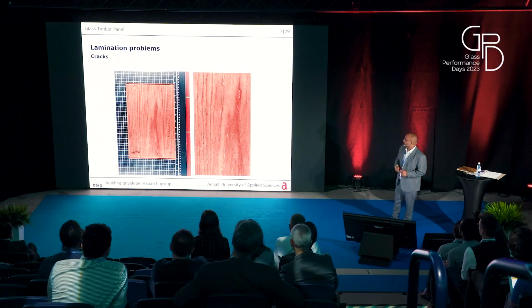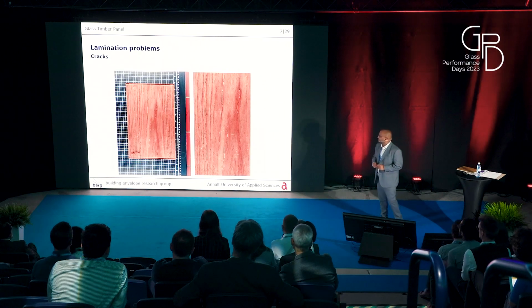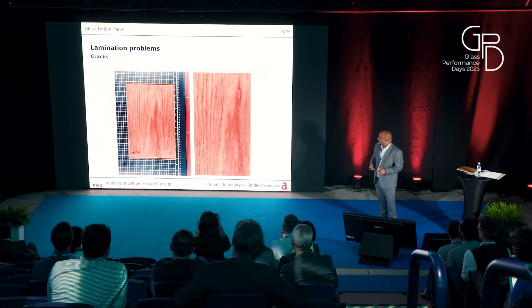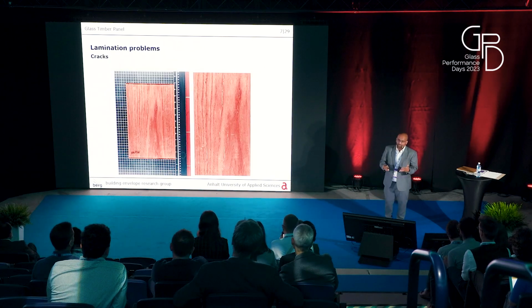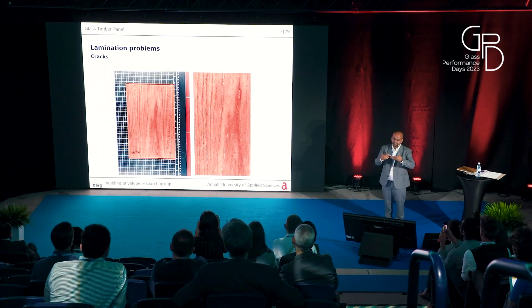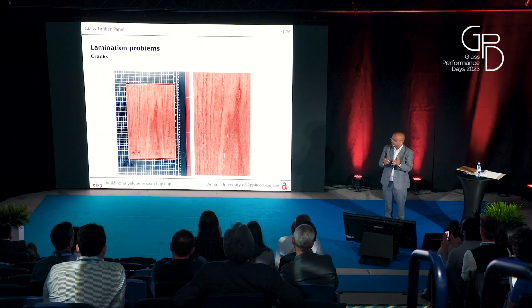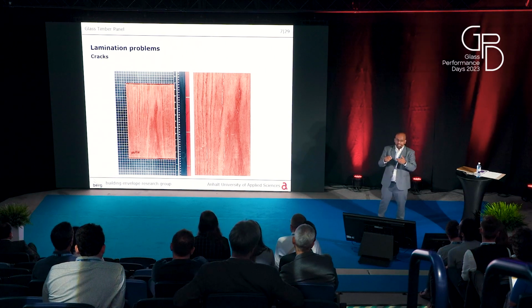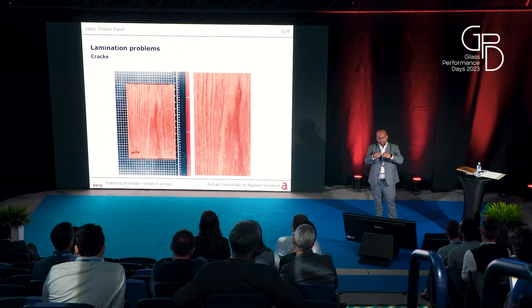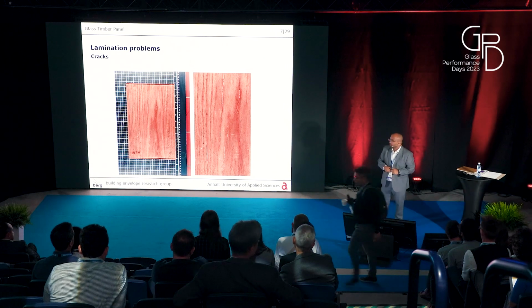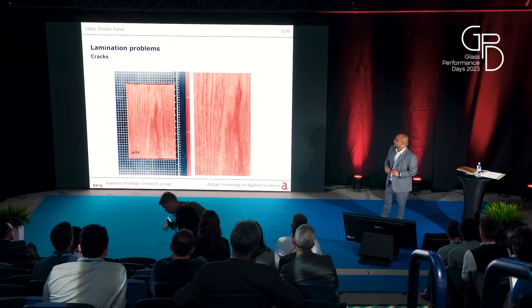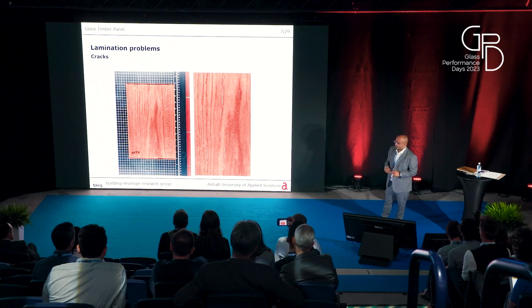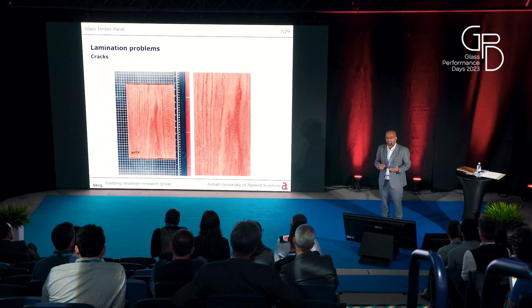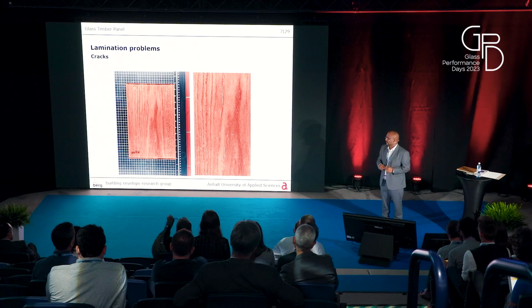The first problem: we had cracks in the veneer. This is due to the lamination. The veneer dries and shrinks, and the interlayer pulls the fibers apart and moves into the veneer. This was one of the reasons. But we tried to compensate with thicker veneer, and we didn't face this problem again.